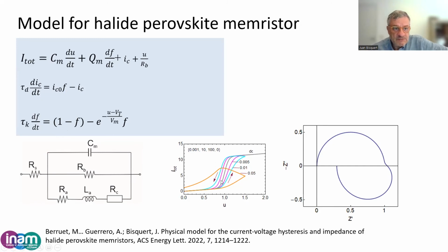So this seems to be very successful because there are very few models for memristors, and this is also an extraordinary result for the analysis of perovskite solar cells, because in modeling the perovskite solar cells, you require very complex drift diffusion simulation with ions, with dozens of parameters, and here you can build a model making very few equations, two or three, and obtain a lot of information about the dynamical characteristics of the behavior of the perovskite device.